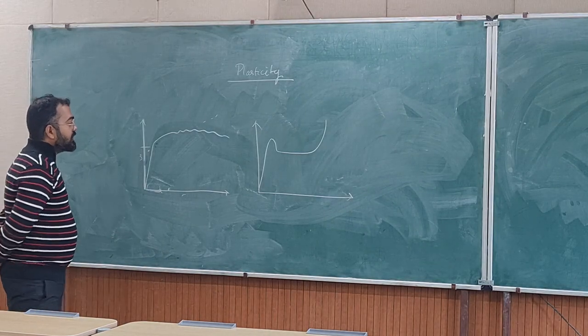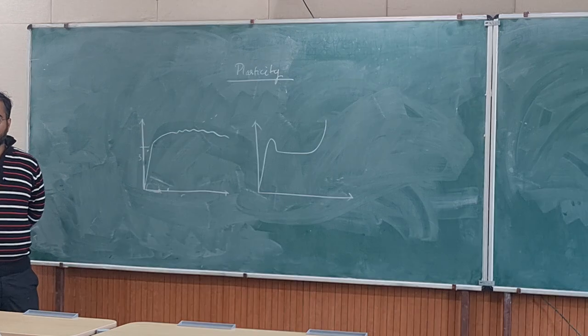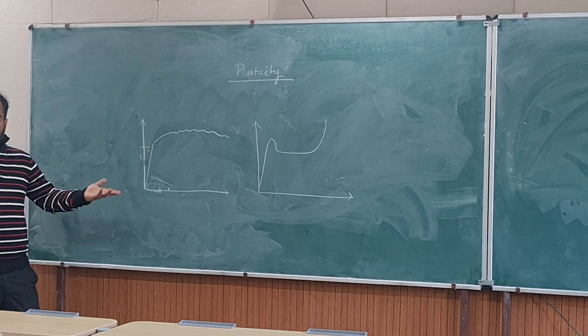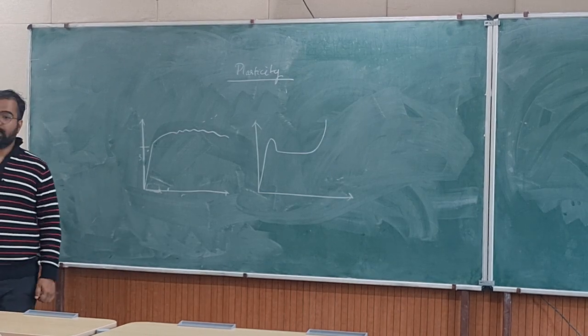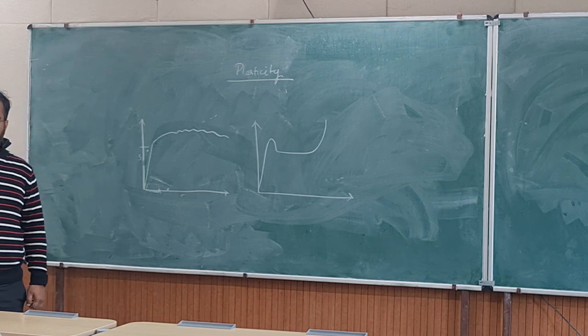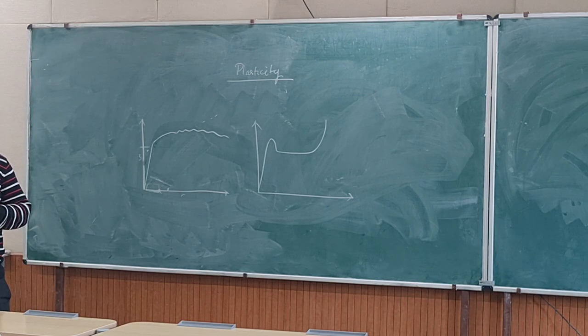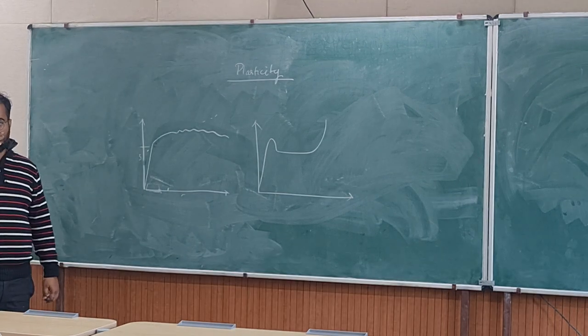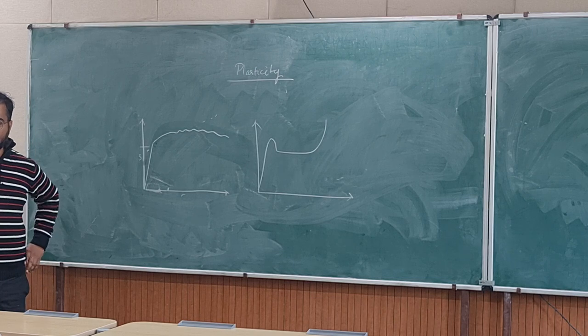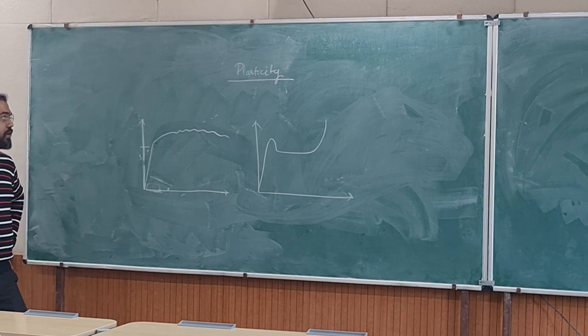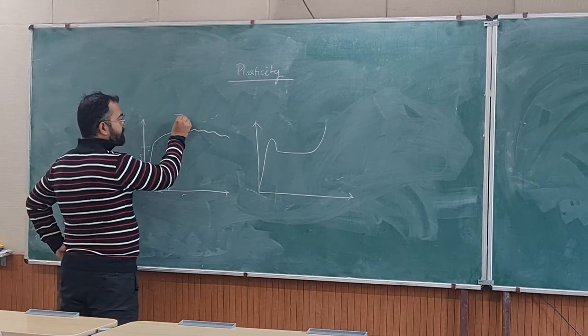So what they do is they will lock the dislocation, and then when a very small amount of energy is available, they will again leave the dislocation there. So now the dislocation will not need much stress to get unlocked. Now it can move, so stress decreases, then they will lock again. And this will go on like a rat and cat race. That is called dynamic strain aging.